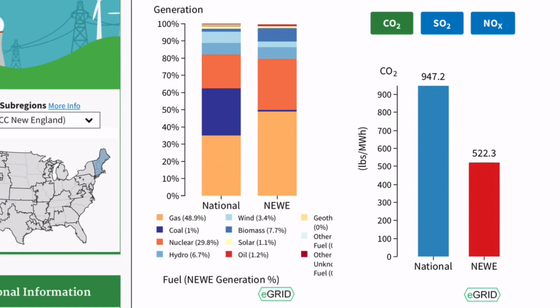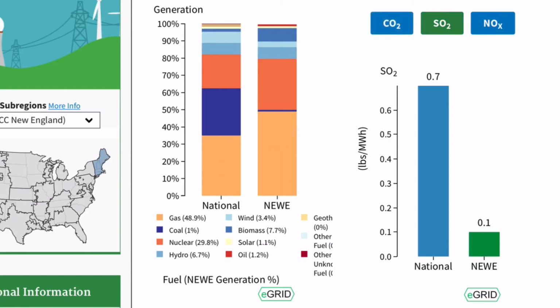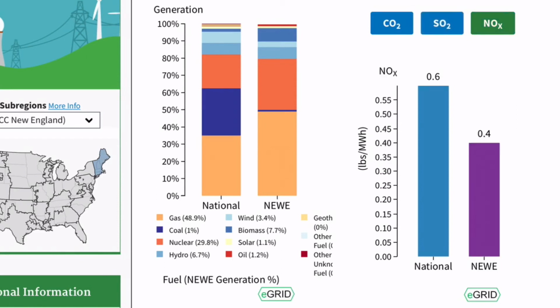For example, we see that New England, based on this NEWE region, has 522.3 pounds per megawatt hour of CO2 versus the national average of 947. If we switch to sulfur dioxide, it's significantly less at 0.1 to 0.7 in terms of pounds per megawatt hour. And nitrogen oxide compounds, again, are 0.4 to 0.6. So this region is particularly green compared to national averages.